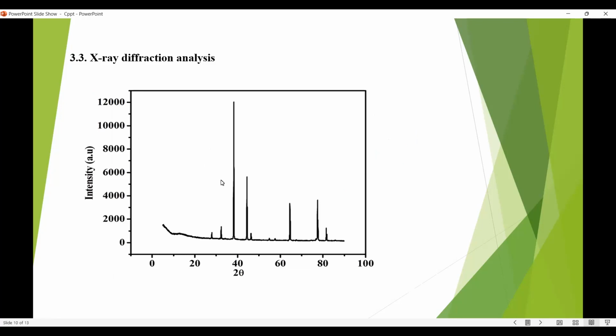Coming to the XRD analysis, the XRD pattern of the synthesized silver nanoparticles was recorded using an X-ray diffractometer with copper K alpha radiation, which has a wavelength of about 1.54 angstrom. It is used for the confirmation of the crystallinity and nanostructure of the synthesized silver nanoparticles. The instrument is operated under optimal conditions of voltage about 40 kilovolts and current 40 milliamperes. So the diffracted intensities with angle of 2 theta.